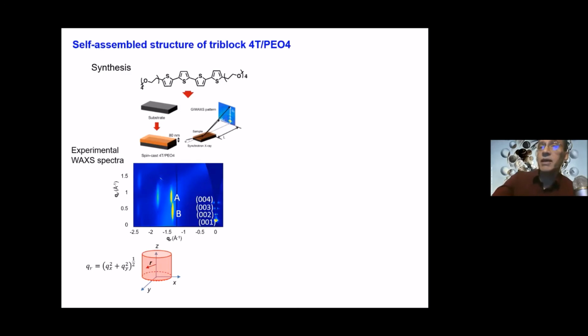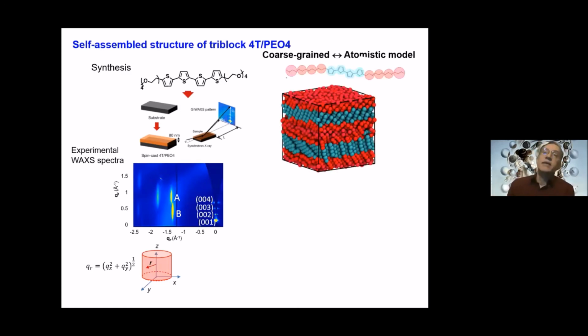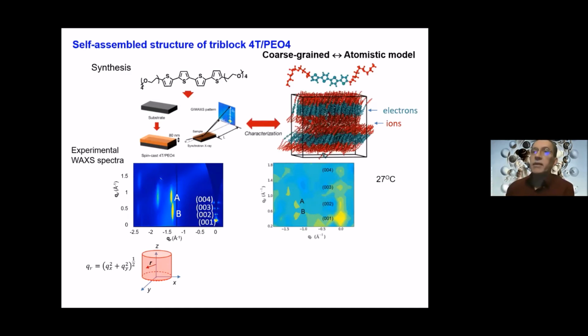So the thing we did was to first coarse grain this material so that it can assemble much faster. And once it assembled, then we can reverse coarse grain it into a fully atomistic model and then relax that system fully so that we get the structure to compare with experiments. And it shows something like this. So you can see in the blue domains are the thiophene rings where the electrons will conduct. In red are the domains where PEO sits and the ions will conduct.